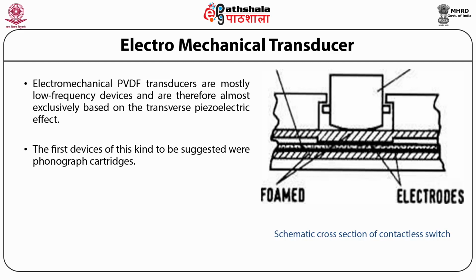Utilizing 1x2 mm strips of PVDF as the transducing elements, a high compliance vibrating system of high resonance frequency is obtained. The 45 kHz frequency response makes such cartridges suitable for the playback of CD4 records.